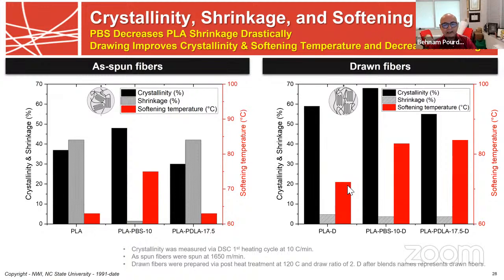It's still low for many applications. If you put it especially in a hot aqueous environment, that would be a major challenge. When you add a little bit of PBS to it, your crystallinity increases, your shrinkage actually reduces to about 3%, your heat deflection temperature goes up to over 85 degrees. And when you add the PDLA, you also get a similar behavior, except your crystallinity is a little bit lower.